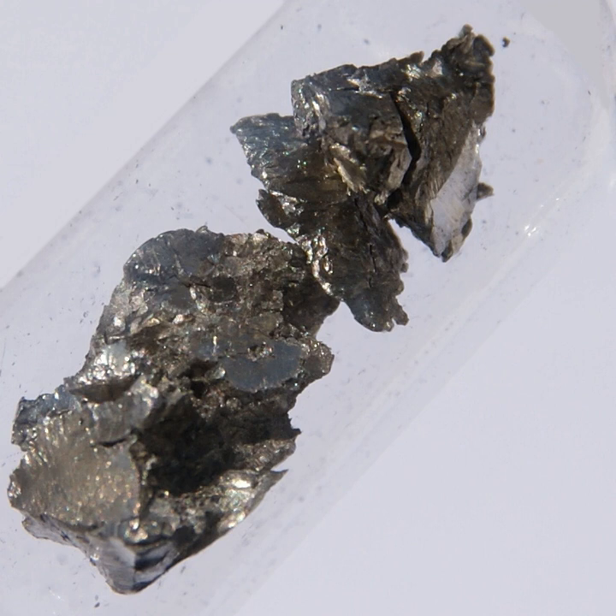The procedure for monazite, which usually contains all the rare earths, as well as thorium, is more involved. Monazite, because of its magnetic properties, can be separated by repeated electromagnetic separation. After separation, it is treated with hot concentrated sulfuric acid to produce water-soluble sulfates of rare earths. The acidic filtrates are partially neutralized with sodium hydroxide to pH 3-4, during which thorium precipitates as a hydroxide and is removed. The solution is treated with ammonium oxalate to convert rare earths to their insoluble oxalates.